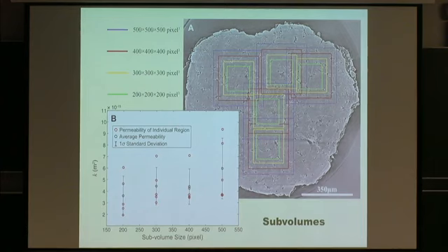To use this, obviously, if you use the whole volume, first, the computation time is really long. Secondly, what you get is an average melt fraction. Whereas with localized subvolumes, if they're large enough, there's always heterogeneity. So you actually can squeeze one sample and have a range of porosity differences. Say, if you put 5% in some regions, you may have 3%, and in other regions, you may have 6%, all right? So that's to our advantage.